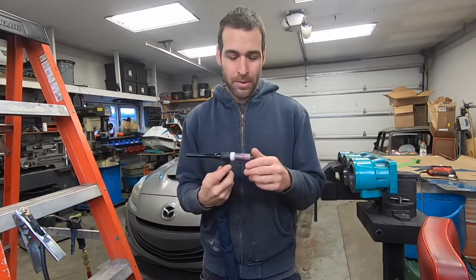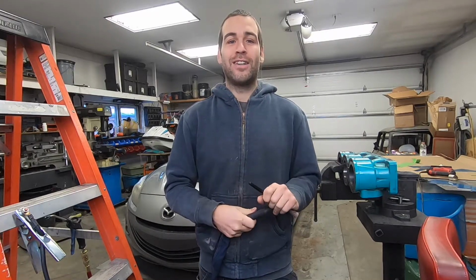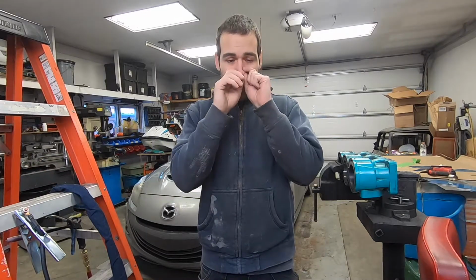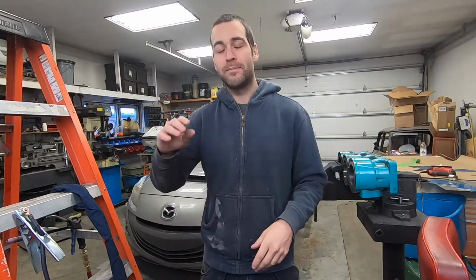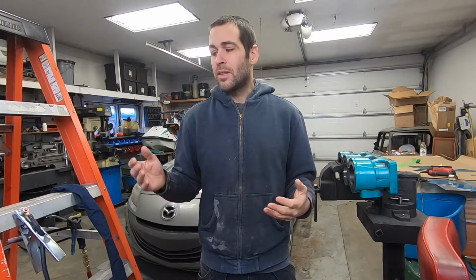I know that was a really long rant, but I've been struggling with this for a very long time. As I said in the video, I've actually gone through 4 tanks of argon trying to sort this out, or I'm on my 4th tank of argon. And sometimes to weld an inch, I've literally spent 4 or 5 hours. So although Everlast is helping me, they're helping me in a very step-by-step way, following a procedure and making sure that they take care of all the gas flow issues and all that stuff. And it is, I mean, necessary. I need to make sure that the gas flows properly. But this machine, in my opinion, has a very obvious issue outside of gas flow, and it's not going to be taken care of by any amount of trickery or accuracy with the gas.